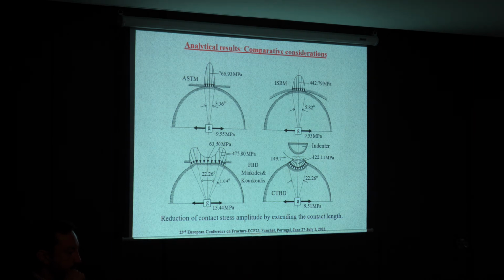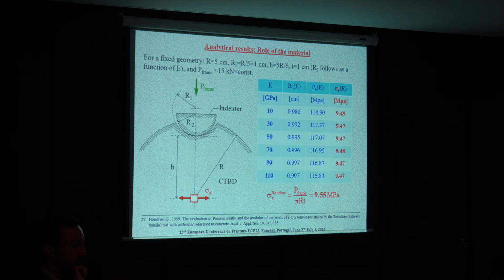And I would like to insist on this slide, where we compare the ASTM proposal, the ISRM standardization proposed by Wang called the flattened Brazilian disc, and this approach. You can see that the stress, which is supposed to be the tensile strength at the center of the disc, is almost similar in the approach of ASTM, our approach, and the approach of ISRM. The one proposed by Wang somehow diverges. But what is most important is to see the maximum values developed. We have here some 750, 450, and 122 stress components at the contact area, which means that a larger variety of materials could be tested with this technique, avoiding premature fracture due to localized cracks at the loaded flattened contact area.